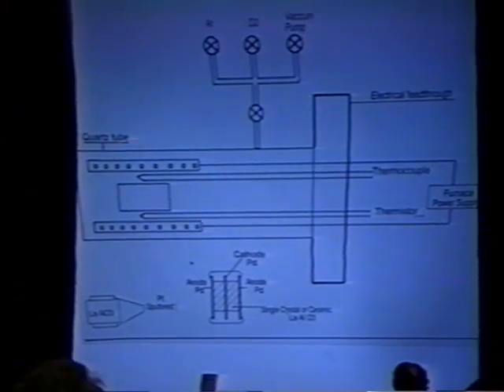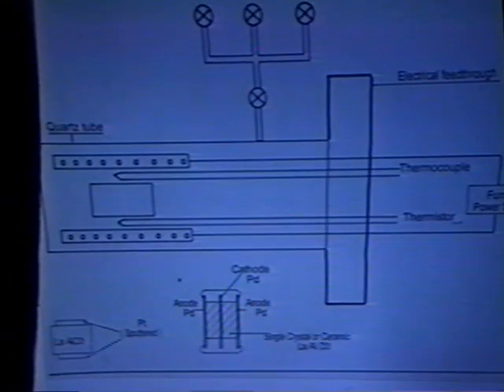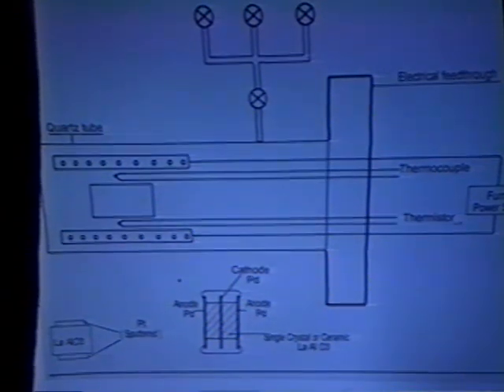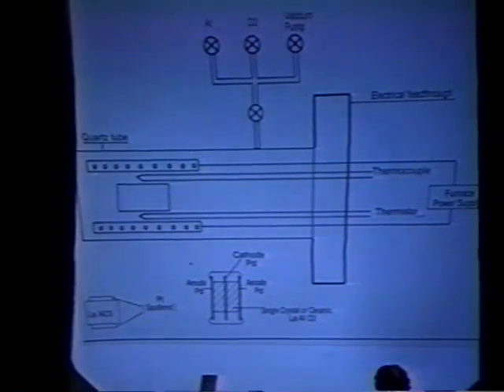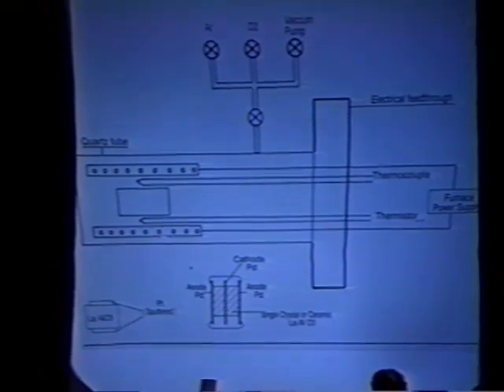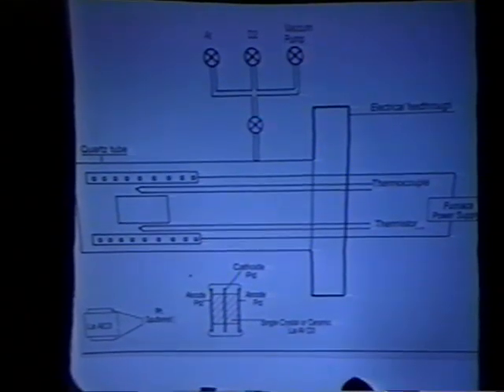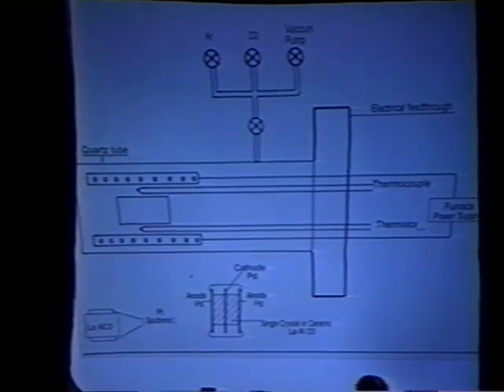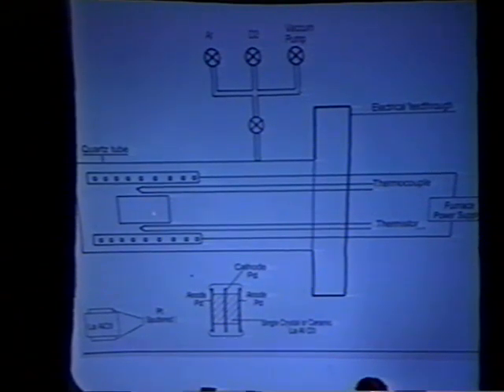So this is just a vacuum chamber, standard ConFlat flange. Inside, we pump it out with a mechanical pump, so in the 10^-2 range only. And we have here a furnace, about 10 centimeters long, and we position our crystals inside the furnace. Our samples are actually made either of single crystals or of ceramics.